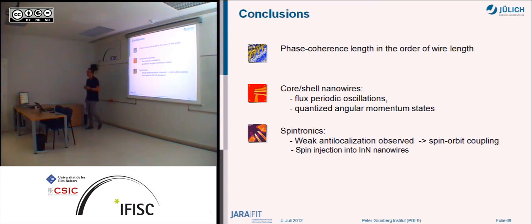Would you expect some signature of the shape, whether it is a hexagon or a pentagon, on the conductance? One thing you can expect is, for instance with these nanowires, you have this hexagon, and right at the corners you expect some potential well. So you have some electron accumulation there. I think there was some Italian group. Some people from Italy did a more detailed calculation, and they took this into account, and what they ended up with was that you can simply assume some quantum well at the corners of the hexagon. And then of course you have periodic boundary conditions, some kind of periodic lattice, and then you can start to calculate everything.